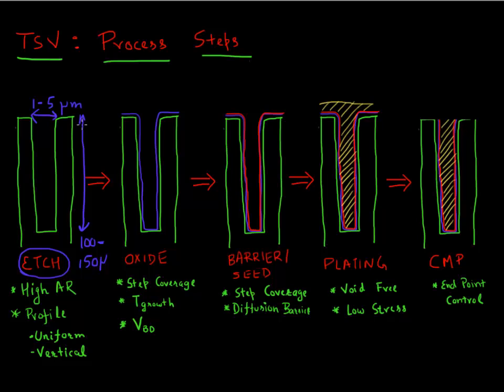At the same time you need to keep it deep enough such that it enables you to connect through the entire depth of your wafer. So that essentially requires that now you have very high aspect ratio for this etch. So this aspect ratio for this etch would be anywhere from 20 to 100. And you want to maintain a uniform profile. You want your profile to be vertical as much as possible and you want it to be uniform. This etch is a very demanding etch. It's a high aspect ratio and you also want to control your profile.